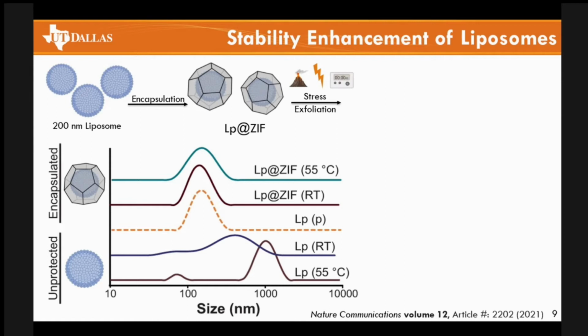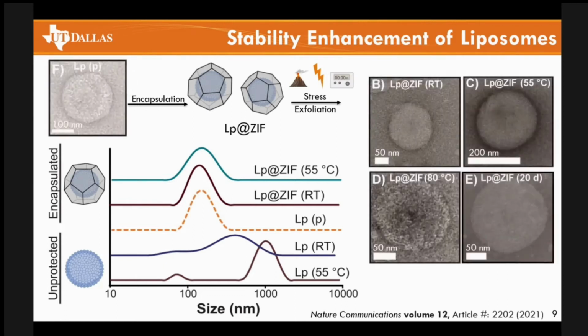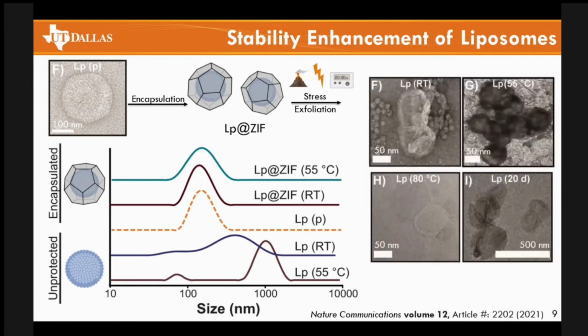We not only did dynamic light scattering characterization of these materials, we took it a step further and we looked at transmission electron microscopy. And the idea, again, is very simple. Stressing at room temperature for 48 hours, at 55 degrees Celsius for 15 minutes, at 80 degrees Celsius for 5 minutes, or at room temperature for 20 days. Okay. As you see from the transmission electron micrographs, the material preserved its structure as a function of the ZIF coating, whereas the materials that had no ZIF coating really suffered from these conditions.